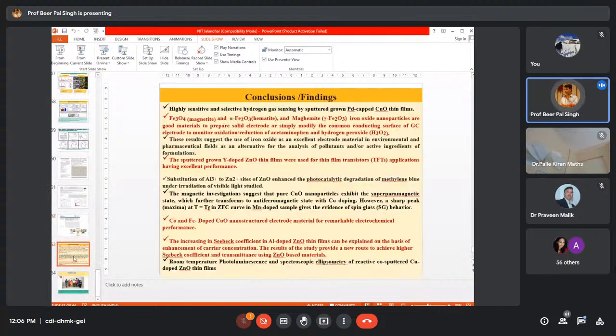These are the findings I have discussed with different materials: the Pd-capped copper oxide thin film which we deposited by sputtering and used for hydrogen sensing. Secondly, we successfully synthesized iron oxide nanoparticles and controlled their phase in terms of magnetite, hematite and maghemite, and we used this biocompatible material for sensing an important drug, acetaminophen, as well as hydrogen peroxide. This research may be very useful for the pharmaceutical industry in the future.